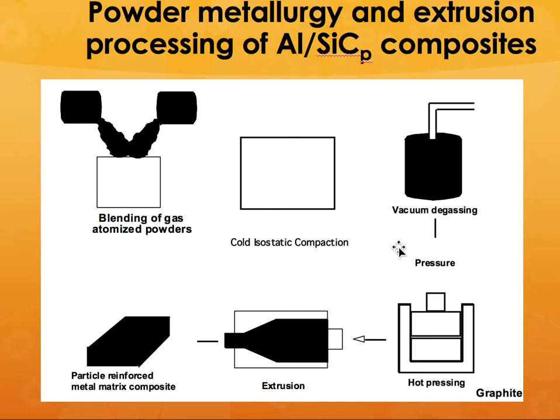You can also do powder processing of these materials. So you take small particles and then you blend them together. You do what is called cold isostatic compaction. Then you hot press it into a shape, and then you extrude that into the final shape so that you can get the fibers aligned in the direction of the extrusion. So you get selective reinforcement in specific directions that you require.